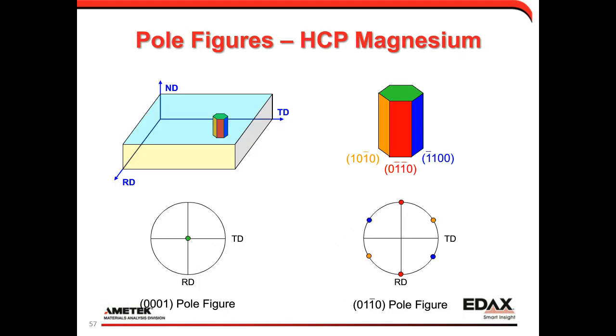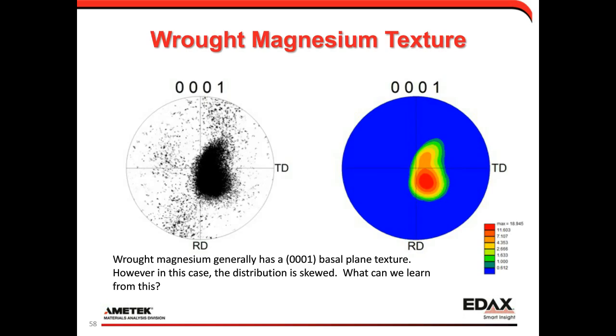So if we look at that here, this just shows a little schematic. We're interested in the 0001 pole. If we have it in that frame, the pole will be pointing straight out. There are other planes that would be possible, but we'll focus on that basal projection. So this is an example from a piece of wrought magnesium alloy. It generally has this strong basal texture, and sure enough we do see a strong basal texture, but it's skewed. It has an upside-down comma-shaped distribution to it. So the question is, can we learn anything from that sort of asymmetrical distribution of the pole?